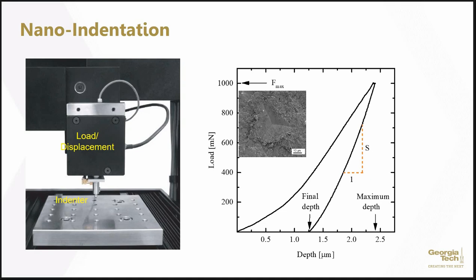Through this loading-unloading curve, you can get properties like the elastic modulus, because we assume the unloading is purely elastic. And based on the load you applied and the volume created during the indentation, you can calculate the hardness and so on. If you can take a high resolution SEM image or microscopic image and see any crack development, you can estimate the fracture toughness as well. So that's an indentation test.